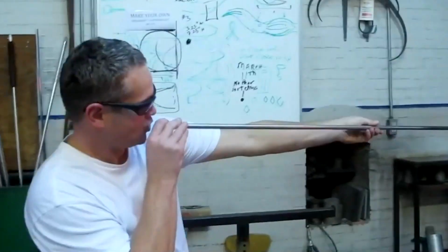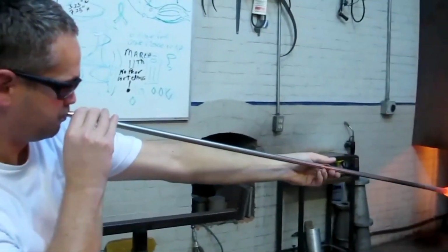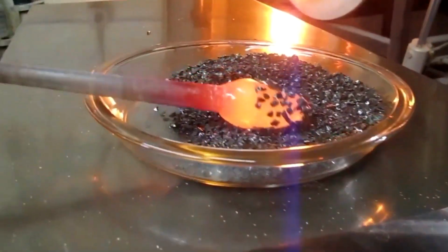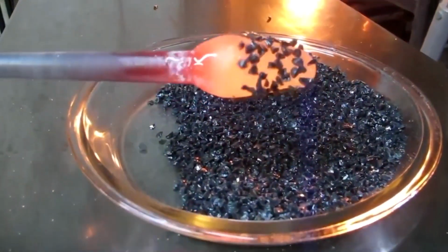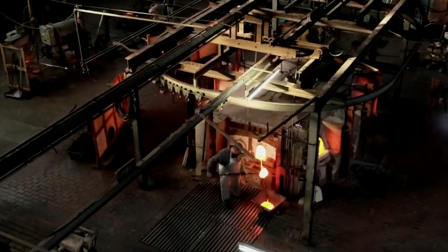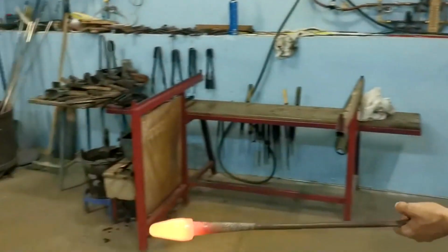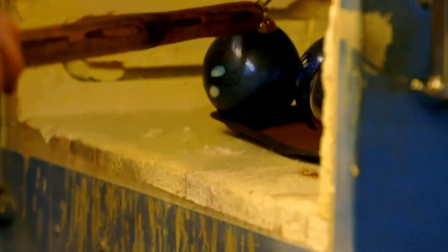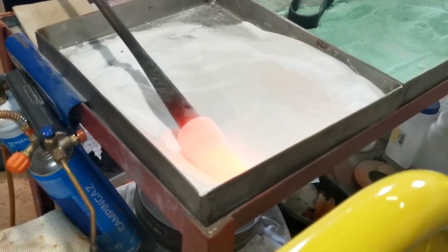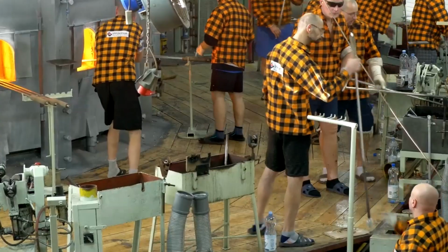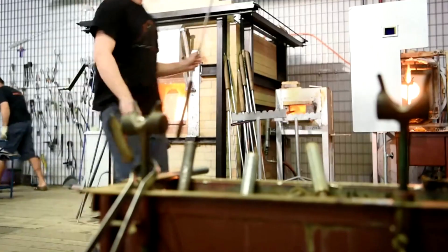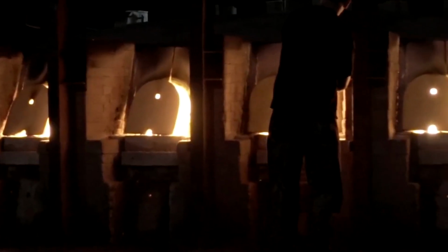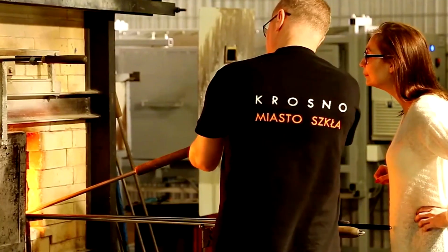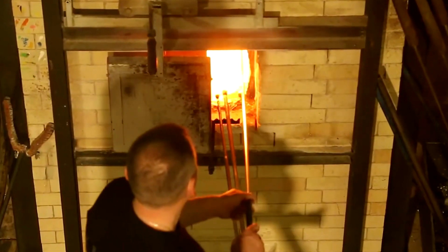When the glass preform is still glowing hot, the artisan brings it into direct contact with trays of fine-colored glass particles, known as frit. It looks outwardly simple to coat the glass in dust, but in reality, this process determines the longevity of the color. Under intense heat, these particles instantly adhere to the surface. Instead of sitting as a temporary coating, the frit softens and bonds with the outer layer of the glass. This allows the color to become part of the material structure, giving the surface depth.